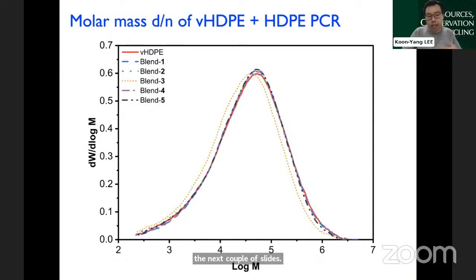When we mix them together, the different types of blends, now your virgin polyethylene mixed with your blends of recycled polyethylene, again, they are as expected. The final molecular weights of these blends are basically the weighted average between those of recycled polyethylene and virgin polyethylene. So no surprises there. So again, just bearing in mind blend 3, it's the one that has polyethylene that are recycled 50 times with virgin polyethylene. So that weighting causes what you see here, a shift towards the lower molecular weight, just because you have much more of those severely recycled polyethylene, if you will.